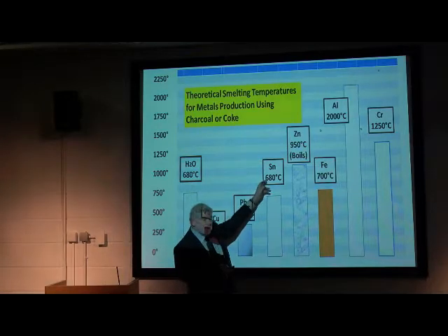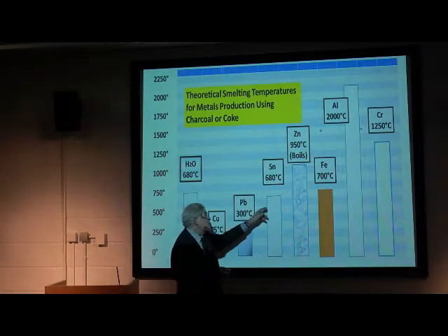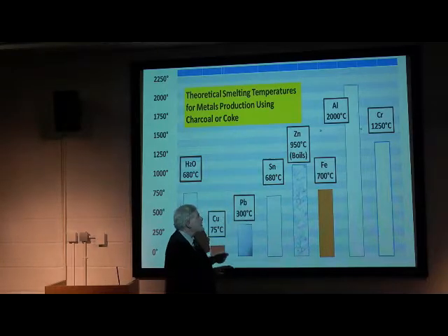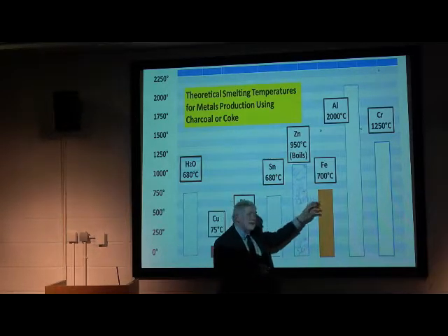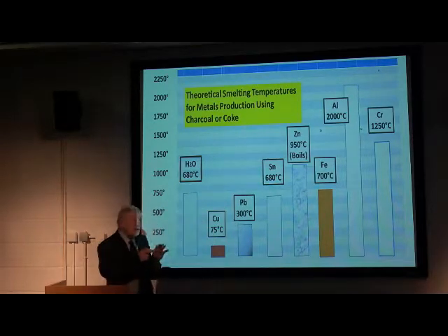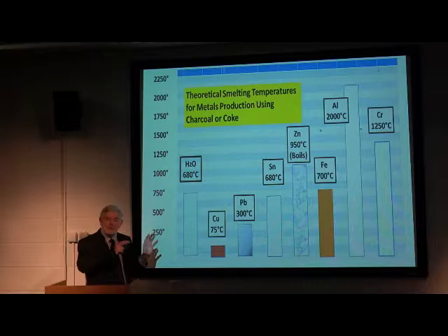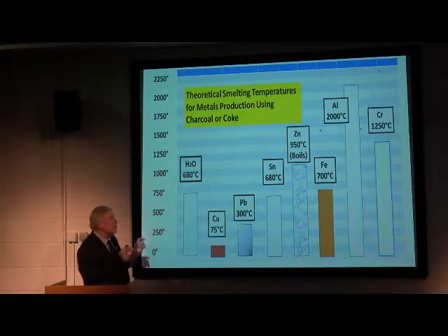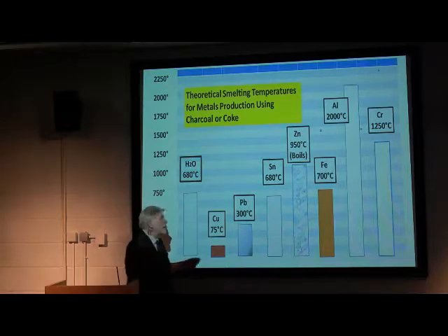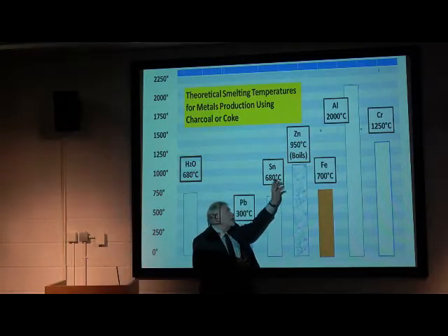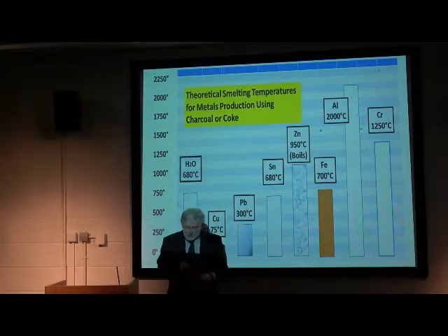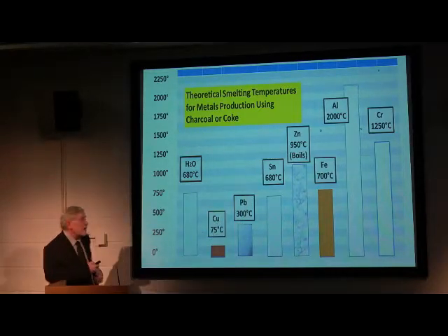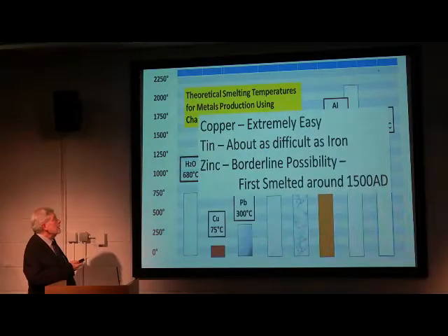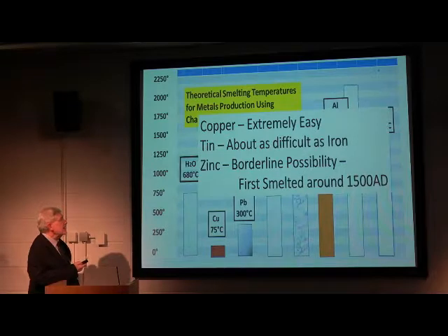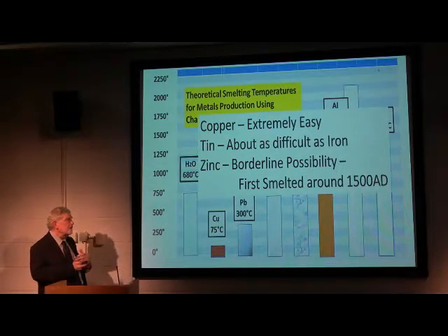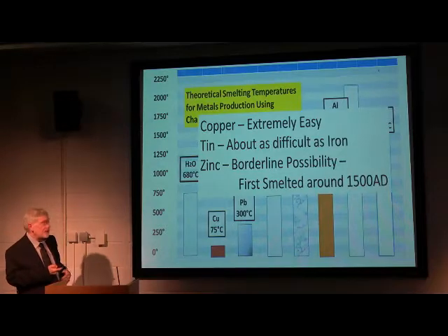But again, you see that tin is hard to produce even by smelting. Almost as difficult as iron. That explains why it took a long time to produce tin, and then not very much longer before iron was produced. And then zinc is quite difficult, and it didn't come out until the Renaissance. Just summarizing it again, copper is very easy, tin about as difficult as iron. Zinc is a borderline possibility.